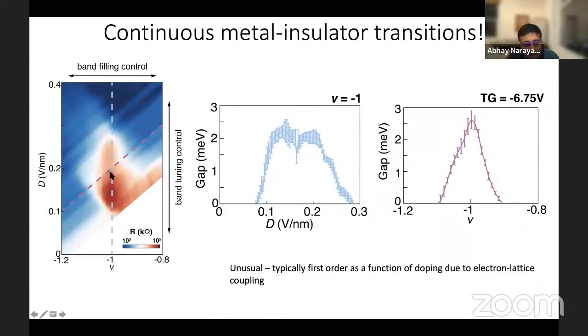So what we do then is we look around this insulating region. So this is this elliptical region. And then we go through this elliptical region. And in this case, we're just measuring transport as you go across this metal to insulator transition. And the first thing we noticed that was very interesting is that if you measure what the insulating gap does as a function of either density, which is this purple line, or electric field, which is this light blue line, you can measure a gap whenever the system is insulating simply by measuring the Arrhenius gap from resistance. And if you measure this gap, you see that this gap goes continuously to zero. So at the metal to insulator transition, it looks like this gap really goes to zero continuously.